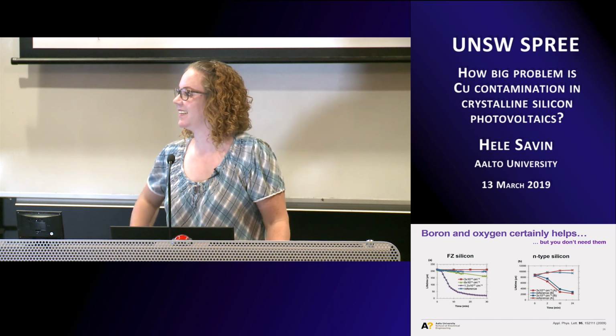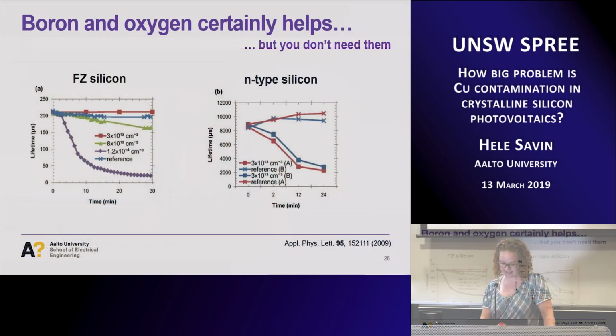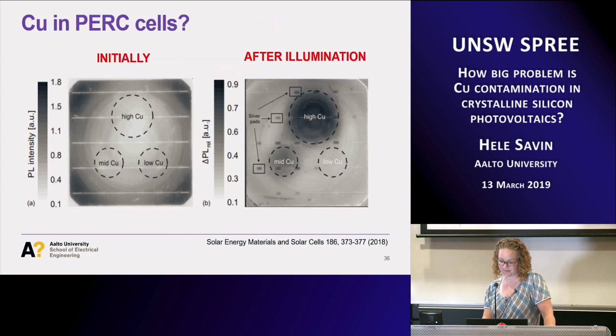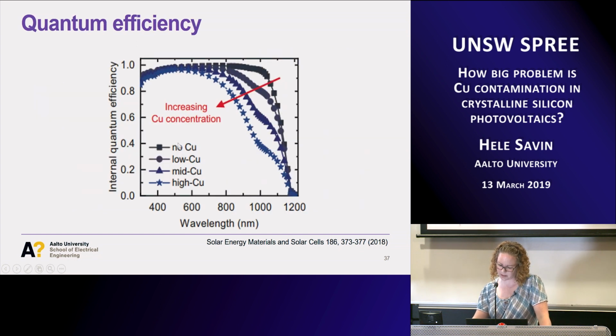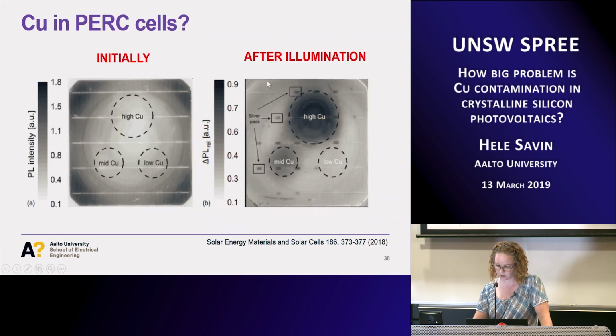So maybe last one. I was a bit surprised that the EQE has such a big difference, although the PL doesn't. What do you think is the reason? One reason is that I believe there is copper also in this background, which is close to this. I have to check, because this is now saying no copper, but I have to actually check if this was the initial curve. That would make more sense, and I could explain it more: it's actually initial and then it starts degrading.